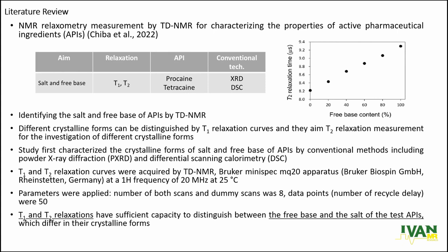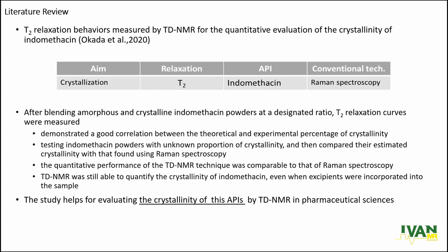Conclude that T1 and T2 relaxation have sufficient capacity to distinguish between free base and salt of the tested APIs, which differ in their crystalline forms. In another study, they used TD-NMR for quantitative evaluation of the crystallinity of indomethacin, which is a model API. They blended amorphous and crystalline indomethacin powders at designated ratios and obtained T2 relaxation curves. They demonstrated a good correlation between theoretical and experimental percentage of crystallinity.